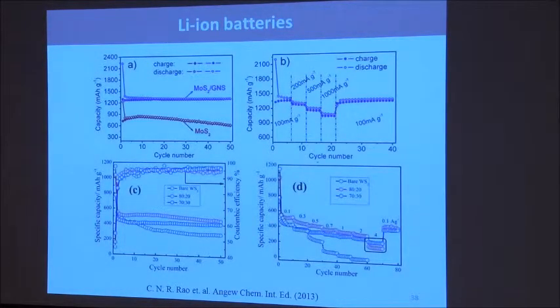One of my colleagues has used these in lithium-ion batteries, with very good performance using molybdenum sulfide as the electrode material, or tungsten sulfide, which is slightly better. Along with graphene, it gives very good performance as an electrode in lithium-ion batteries.